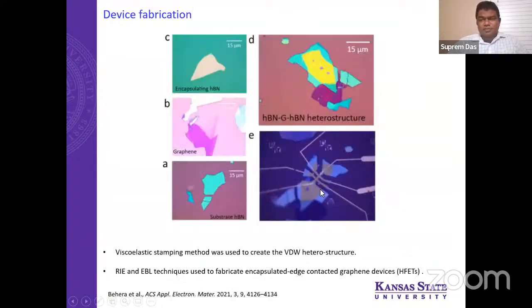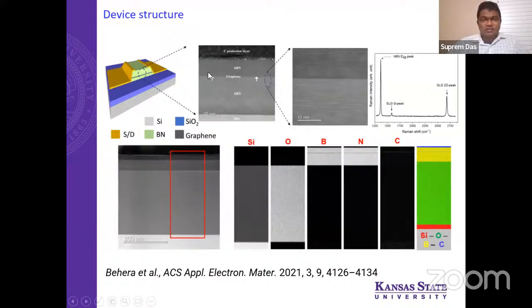Now, if you cut it and look at the cross section, it looks like this. This is the schematic of the device. Of course, it is hard to see where the graphene is, but in this one you can see a little more clearly these lines. These are hexagonal boron nitride. This is the top hexagonal boron nitride, and in between, you have the graphene. If you do not believe this TEM, then you have to believe this Raman, where you see a smaller G peak and a much higher 2D peak. That means it's single layer, and you also have the hexagonal boron nitride peak. That means it has to be hexagonal boron nitride, single layer graphene, and hexagonal boron nitride. Also, you can have elemental analysis where you can monitor each and every element.